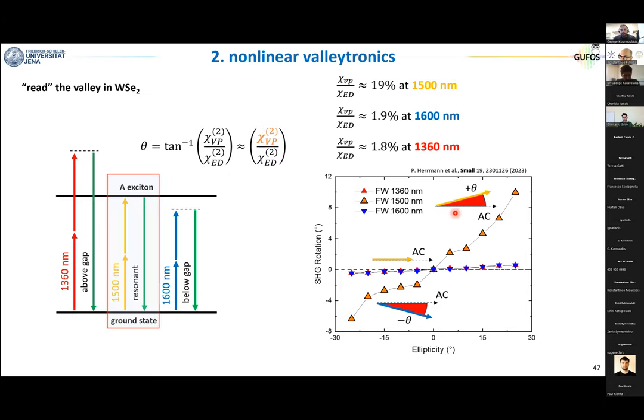And now, of course, you can do this for different values of the wavelength. I was only talking about the resonant case, where we go at 1.5 micron that is resonant at 2 omega with the exciton. But if you do it below gap or above gap, it turns out that when you are at resonance, and this is probably obvious because this is when you're really probing the valleys, then you have a rotation angle that is one order of magnitude stronger compared to the off-resonant case, so above and below gap.